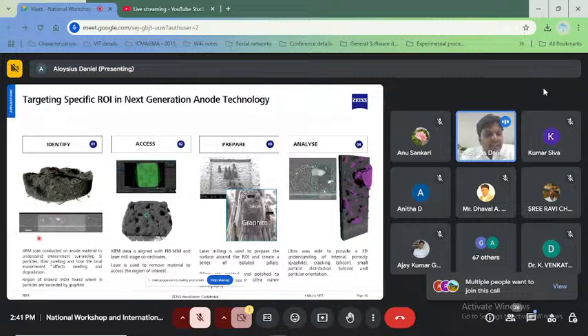So usually we take the electrodes in the battery industry. Once it is manufactured, once it is packed, they do a complete analysis. They identify certain regions of interest. It could be a failure, or it could be a deformation from the actual fabrication or the manufacturing process, using the X-ray microscope. Then once it is identified, they use the laser beam for removing the material and exposing the region of interest. Then the FIB column, the ion beam, is used for preparing the samples, and then they want to understand the analytics of it.